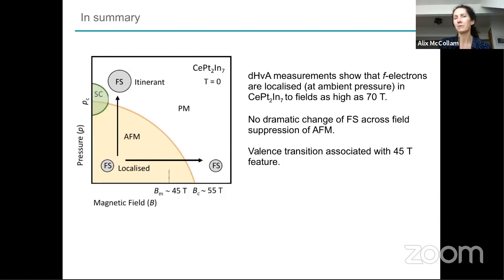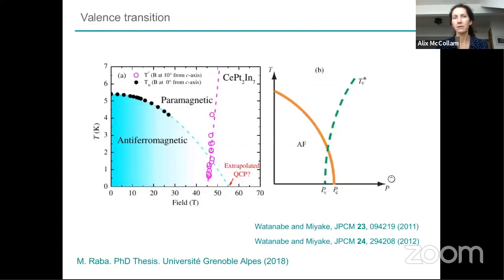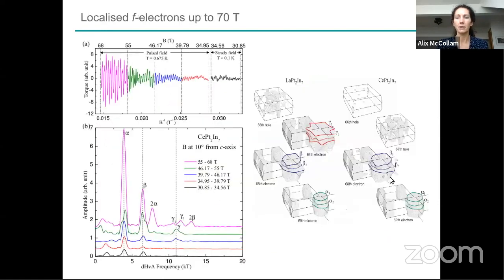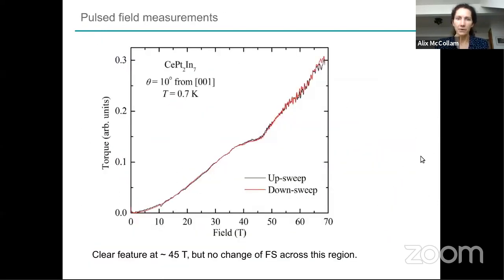So we should be able to see it, but all we see is a rather flat but clear feature around 45 Tesla in the torque, which is the one that I showed you. But the quantum oscillations don't change much. So there's this behavior at around 45 Tesla, but although the background of this torque curve is changing, the oscillatory part on top of that doesn't change very much at all. So we don't see anything really changing across there, except the mass.